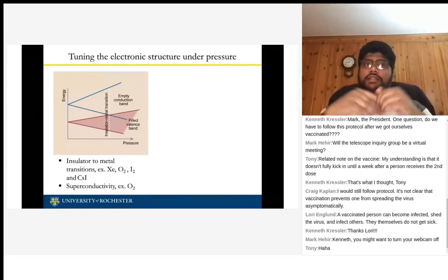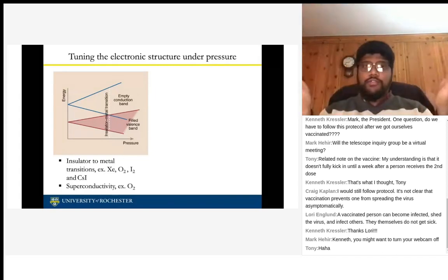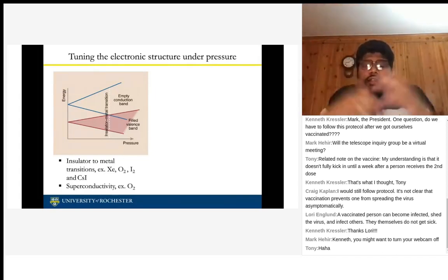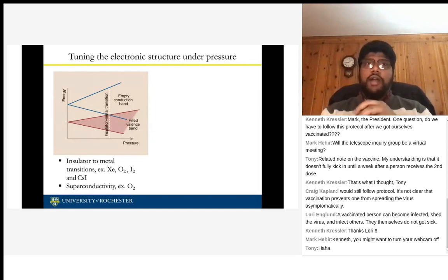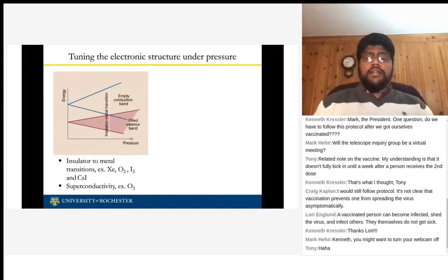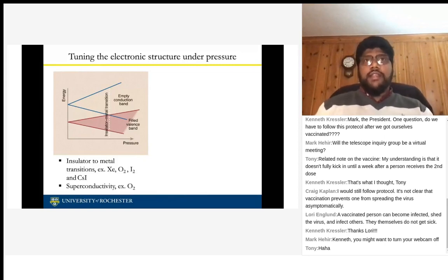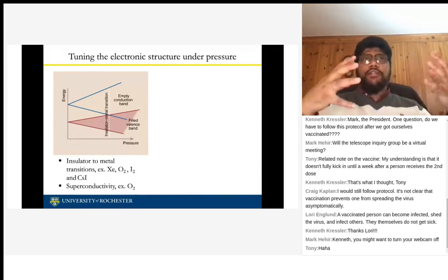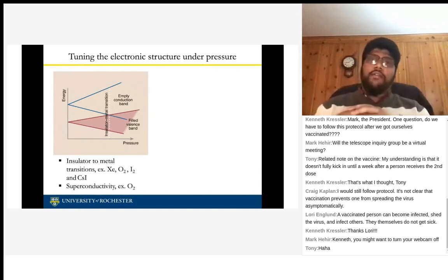For example, xenon is a noble gas. There's no interaction or chemical bonds. It's an inert gas. But if you pressurize it to high enough pressure, for example 1.3 million atmospheres, it becomes a metal. So all of a sudden, a noble gas becomes a metallic material. Oxygen, iodine, cesium iodide, those are examples. And oxygen is not even just a metal, it's a superconducting material as well. So you can think that if you take any material and subject it to really high pressure, you can make a metal out of it.